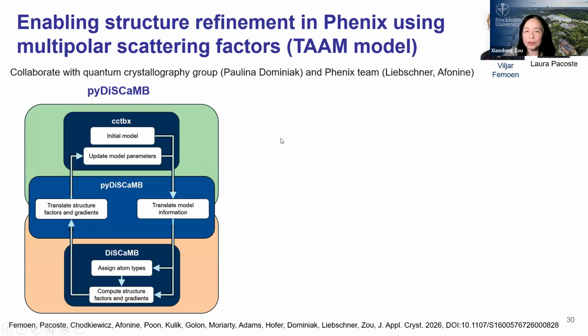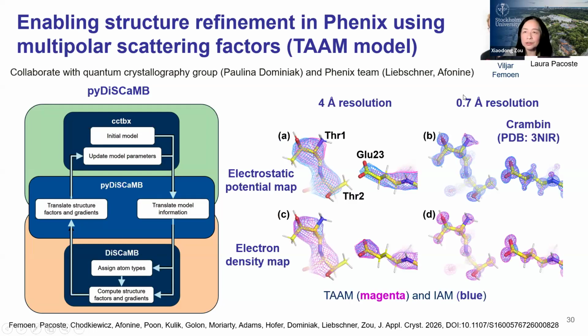And just for your information, to show the advantage, you can see here when we use the TAAM model at very high resolution, this is the simulated data. Using all data, the two models, this is the electron density, this is the electrostatic potential, you don't see very big differences. The important thing is that the low angle reflections, I showed you the scattering factor, differ a lot. It's below 4 angstrom. When you use that, the electron density is very similar, but from the independent atom model versus the TAAM model, you can really see the charge a little bit. This is the difference between these two.